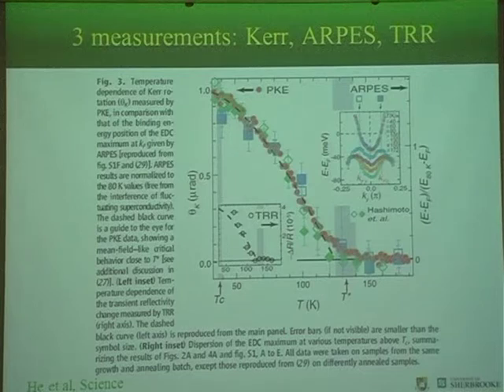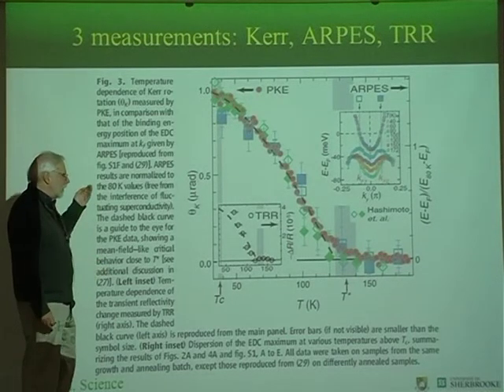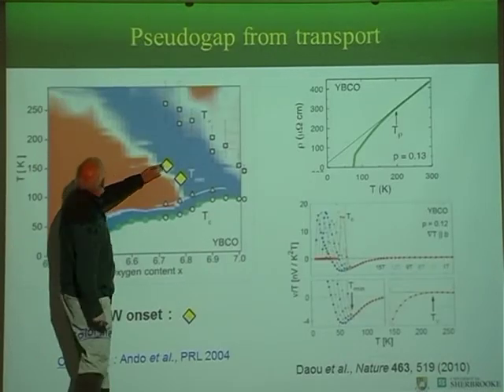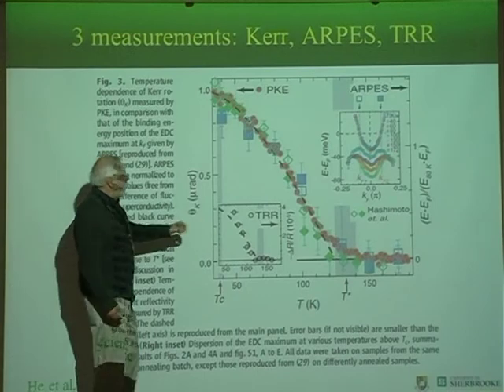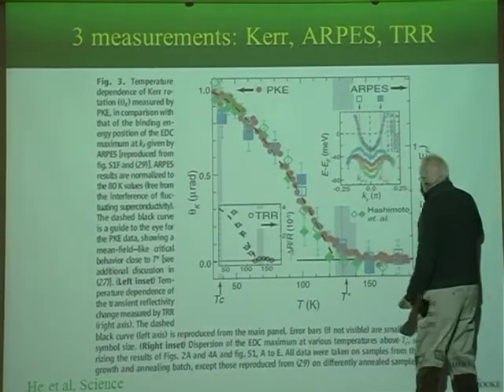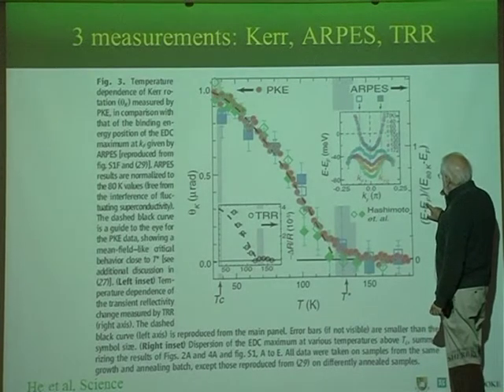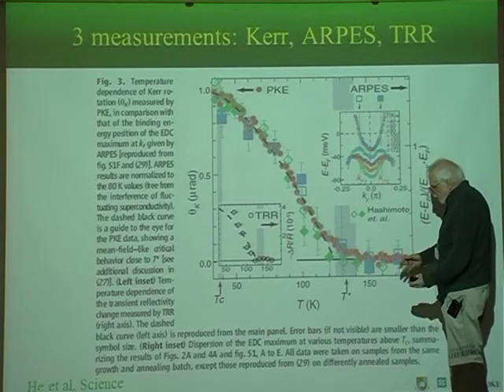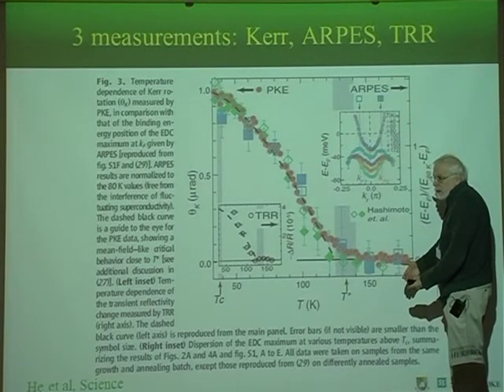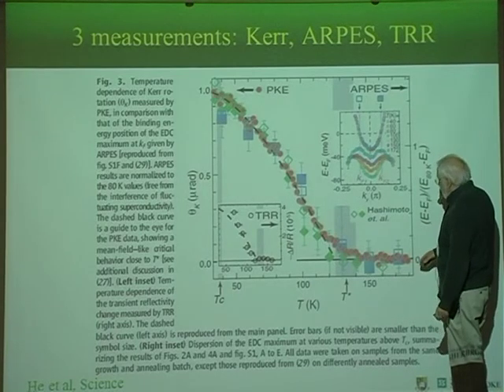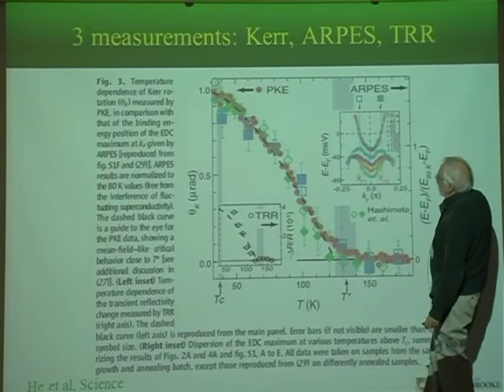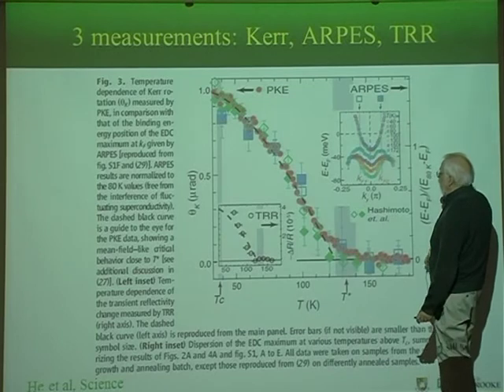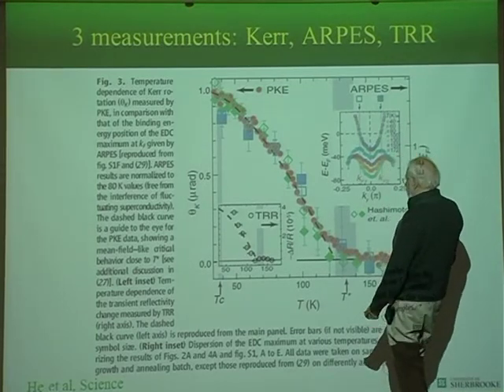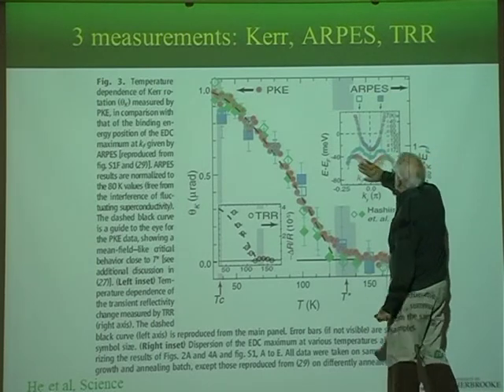Now these are other experiments for the same compound, the same doping, this doping here, where the transition is at 150 Kelvin, where they have measured now the leading edge shift of the ARPES measurement. So in other words, there is this removal of weight from the Fermi surface, and you look where it first appears. That's called the leading edge. So as a function of temperature, this is this scale here, and this is in black, I think. I forget. And then okay, so this is the ARPES measurements, and well, the final result is one of the lines here. I forget which one.